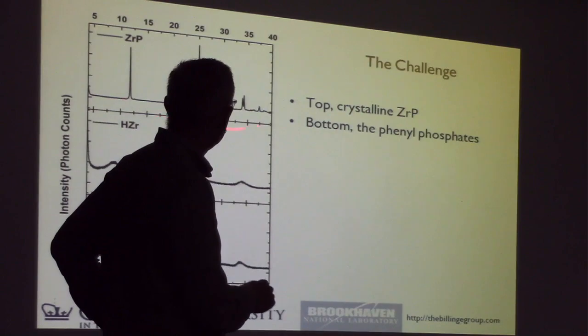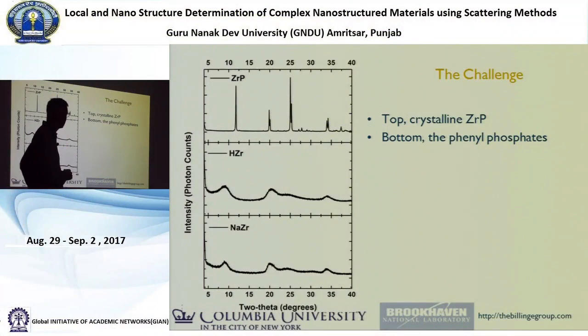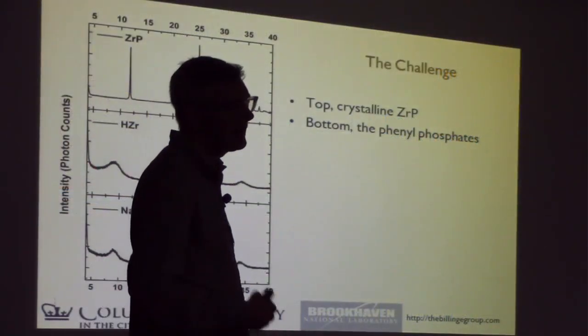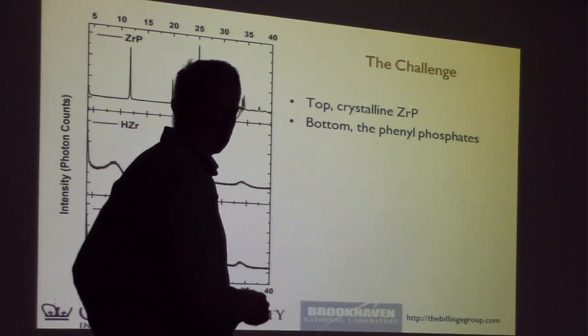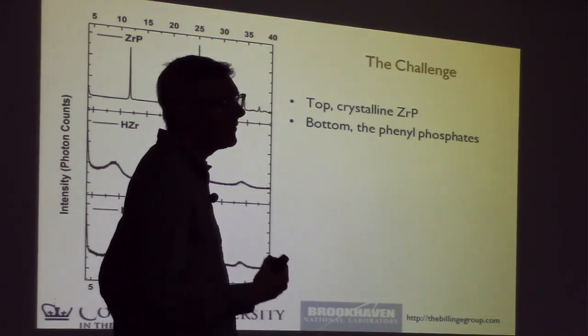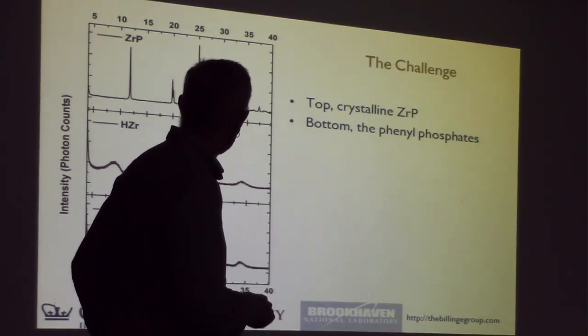Now, the problem that I ran into is that this is the powder pattern from a crystalline, purely inorganic material, but from his hybrid organic-inorganic materials, the diffraction pattern looked like this. And whenever you're faced with a diffraction pattern that looks like this, you should think about using PDF. So these materials, they have a little bit of structure, very broad peaks, but they're nano-sized. So these particles of this material are extremely nano, and there's no way that you're going to solve the structure from this.